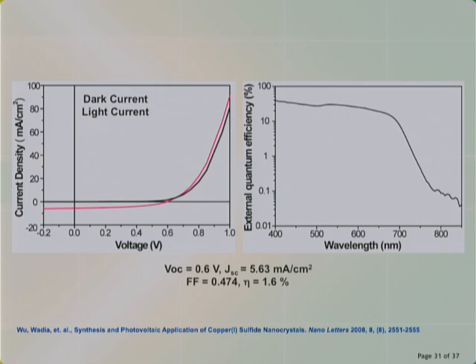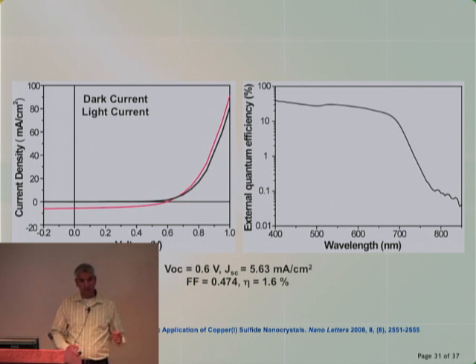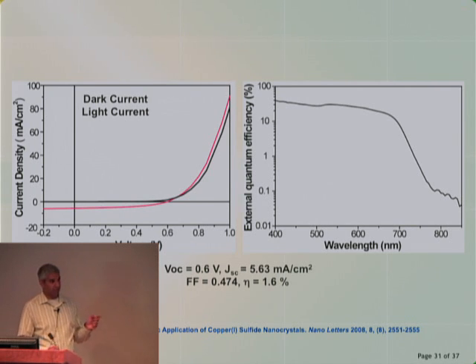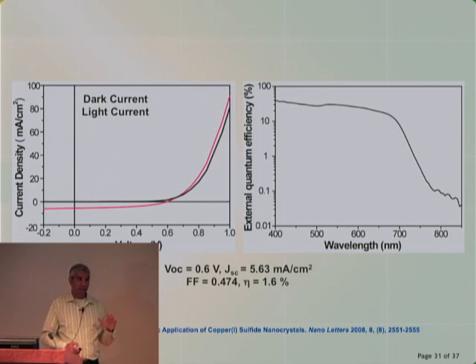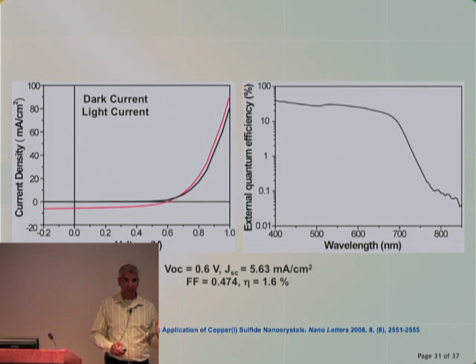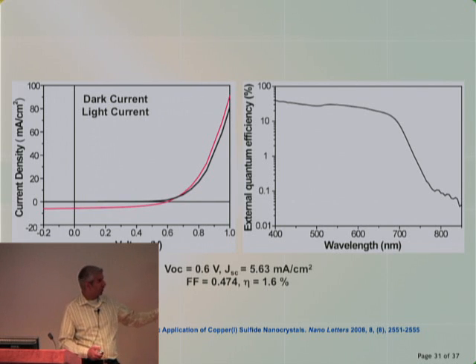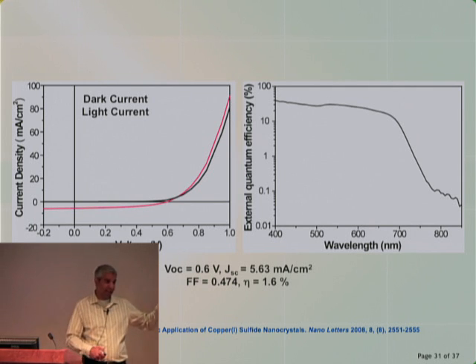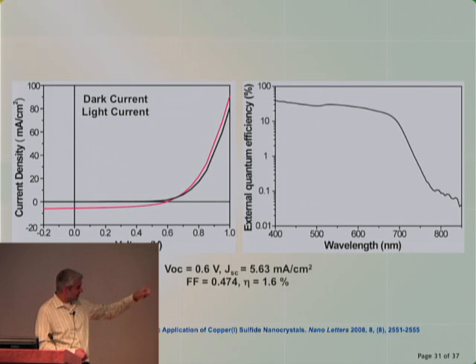One other thing that I show here is called the external quantum efficiency. The other thing I'm going to point out here is copper sulfide absorbs to about 1,000 nanometers. But here we see a sharp drop-off after 700 nanometers. This is probably due to some intermediate defect state that's introduced when copper diffuses from copper sulfide into cadmium sulfide. It's a known issue with bulk semiconductor copper sulfide and cadmium sulfide. We don't know yet at what rate ours are subject to this. But when I saw this, I recognized that and thought, at least this is a problem that we can identify and figure out how to solve immediately. And then from there, we can work upwards of 1.6%.